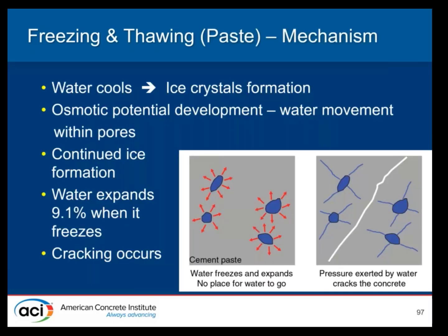So what does that look like? What's the mechanism? In non-air entrained concrete, as the water, which is a weak alkali solution, cools, ice crystals form in the large capillaries. Osmotic potential develops and causes the movement of water from unfrozen pores to the frozen ones. More ice forms until the cavity is full, and once it's all full, cracking starts to occur. So basically what's happening is this water wants to freeze, it's expanding, it's got no place to go. Eventually it pops the concrete. That's on non-air entrained concrete.